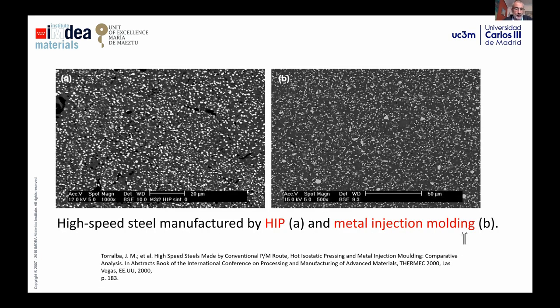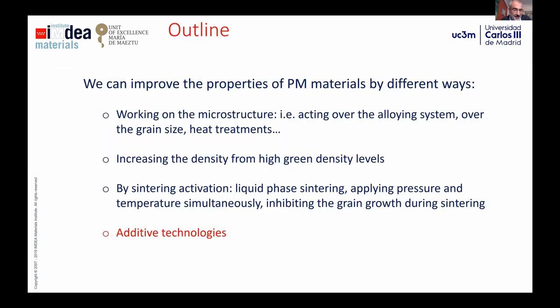This is one example in which you can compare one high-speed steel on the left, produced by hot isostatic pressing, and on the right, metal injection molding. You can see more or less the same microstructure by different routes. So that means powder metallurgy offers a lot of different possibilities to get, at the end, one suitable microstructure for one specific application. And let's go to the fashion of the last times, which is additive technology.